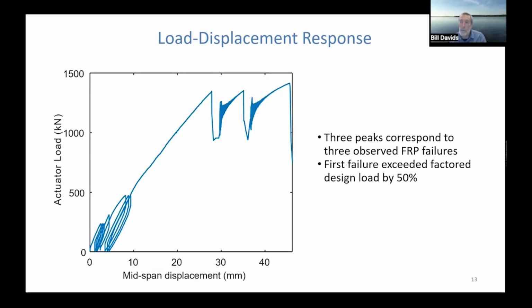And I'm going to give you right off the bat what happened when we loaded this. So this is the plot of actuator load versus midspan displacement of the specimen. And we are cycling load from 50%. We went up to 50% of a service load a few times. We went up to the full service load a few times. And then we drove this thing to failure.